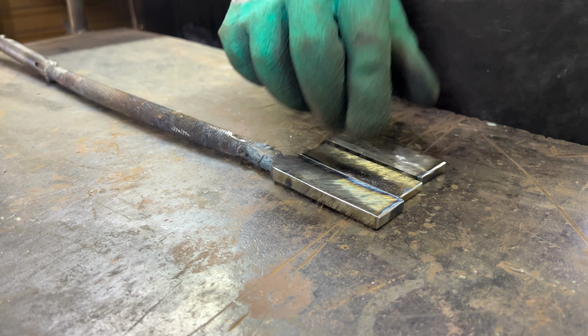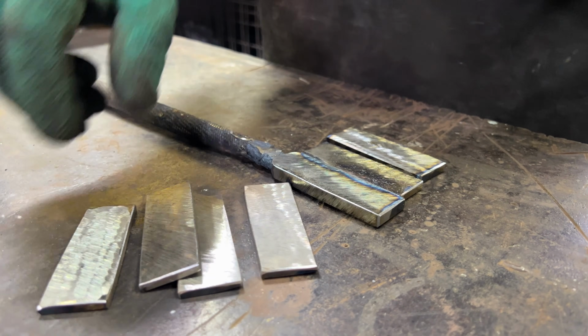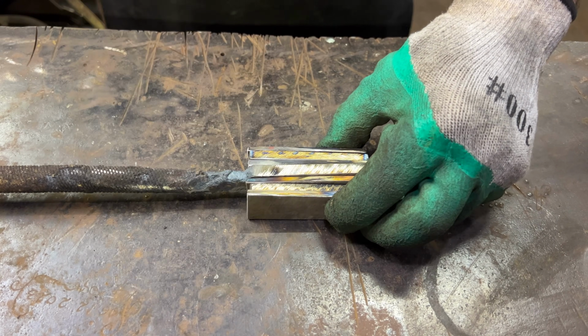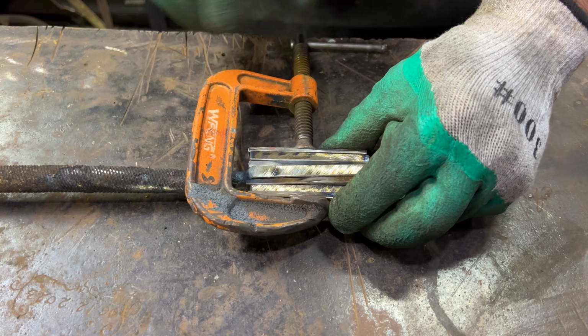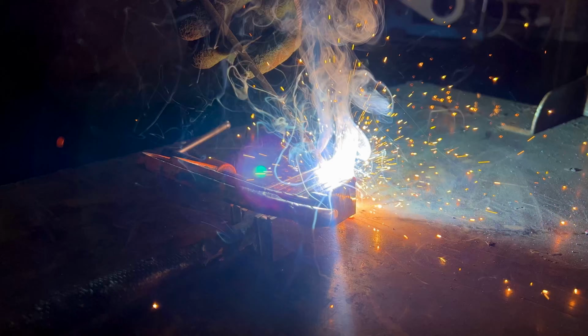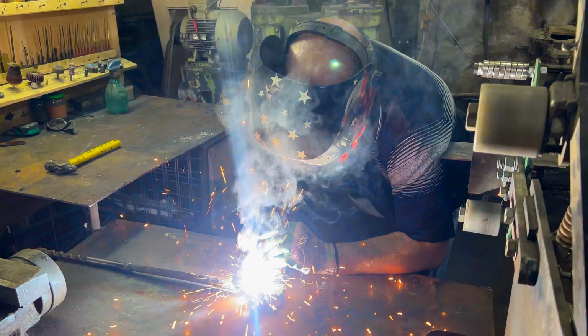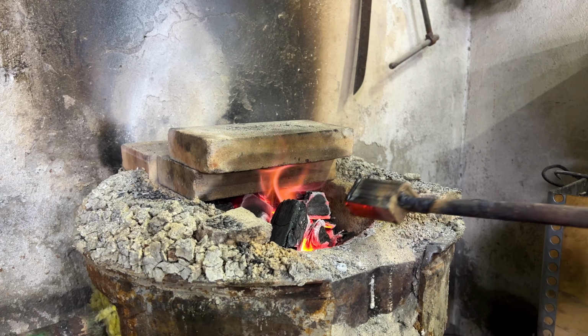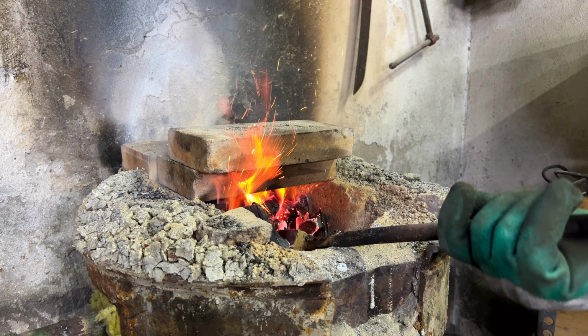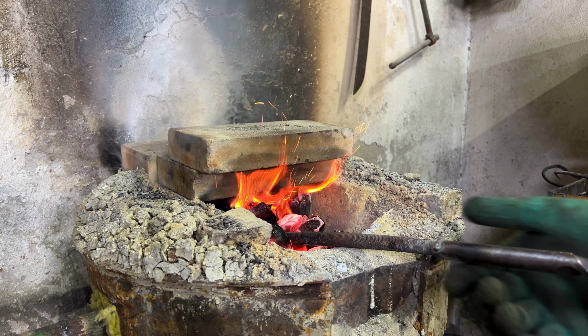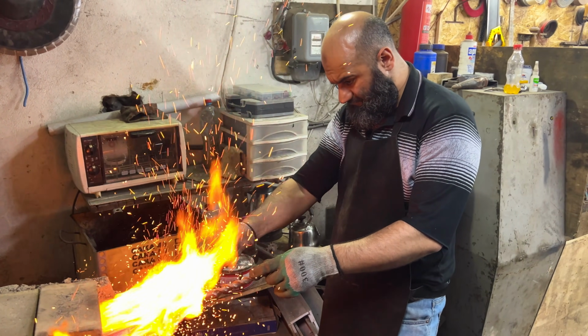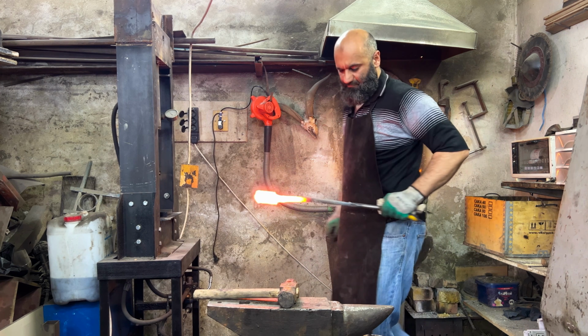Stack them up. I'm welding these 4 clean plates together to form a new, denser billet. Back to the forge, more borax, more heat. We are essentially doing the same process again. Heat, flux, hammer, repeat. This is called forge welding. You have to be aggressive but precise. If there are air pockets inside, the final blade will have holes, and I will have a very bad day.